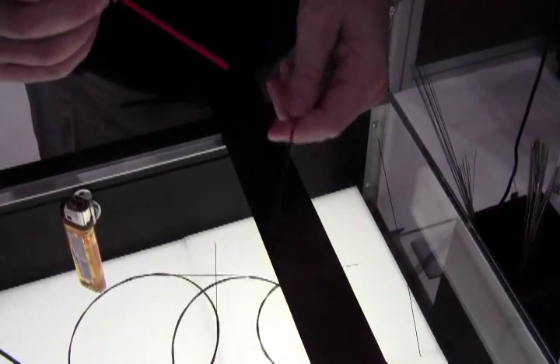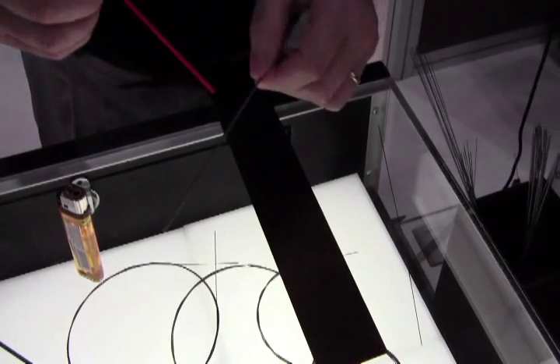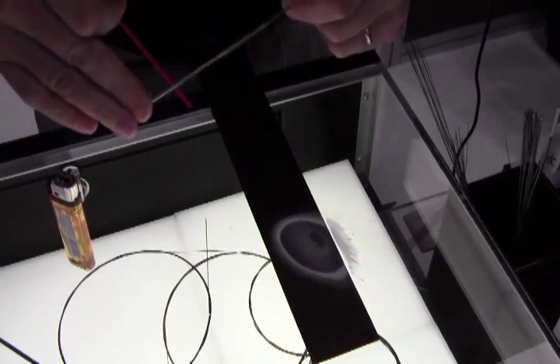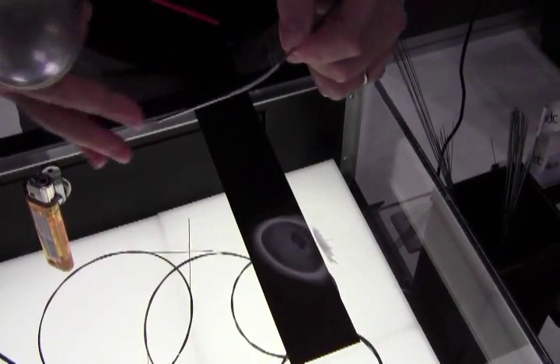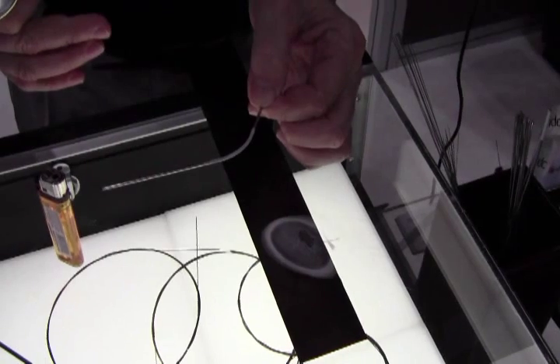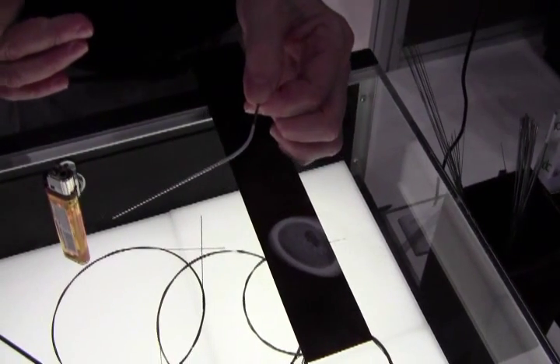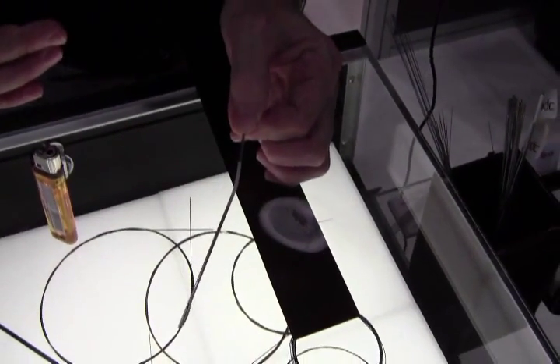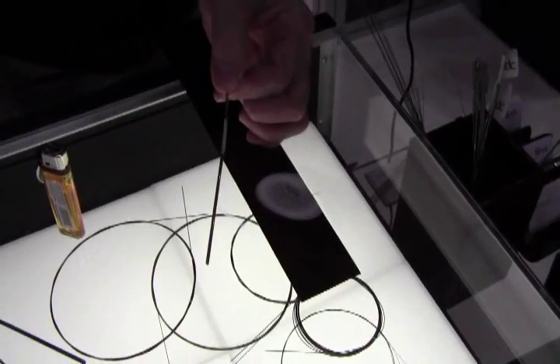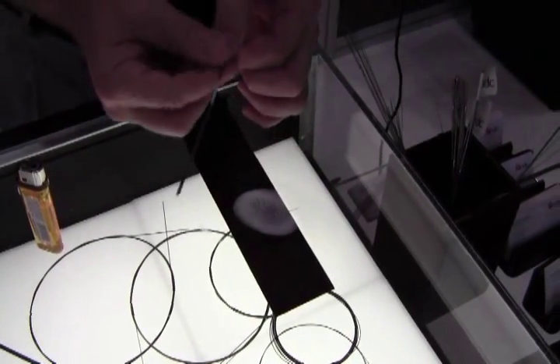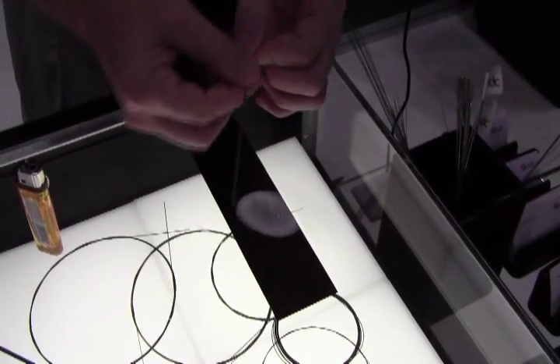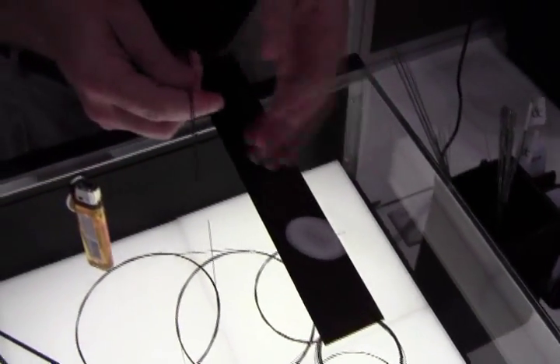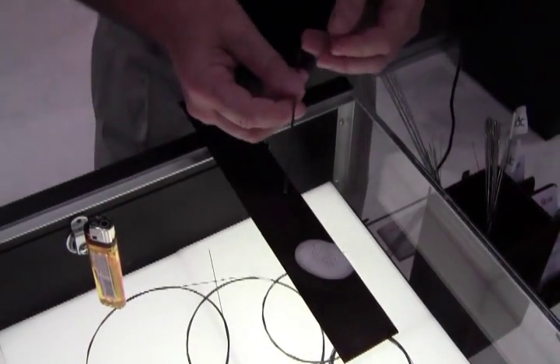When Nitinol goes through a temperature change it goes through an austenitic to martensitic phase transformation. By cooling this down what I can do is change it into martensite, deform it, and as long as it stays cold it'll be deformed. But you can see as it heats up it returns above that transformation temperature and goes back to its austenitic or super elastic nature as it was before. So all Nitinol has both thermal and elastic shape memory, it just depends on the temperature.